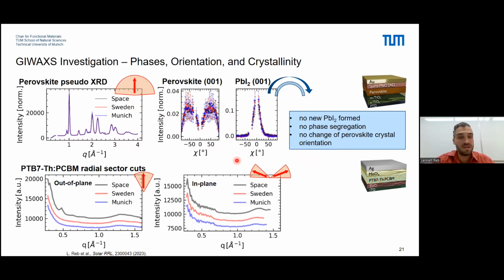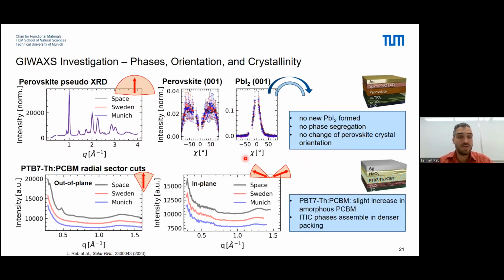The organic solar cells, however, show that there are slight changes in PCBM. So here I'm just showing you the fullerene, and we have a slight increase, which is possibly due to a slight agglomeration, which we also saw in GISAXS, which you can see here that there is a slight increase for the space samples. And also for the ITIC, the small molecule acceptor, we can see that the phases assemble in a little bit denser packing.